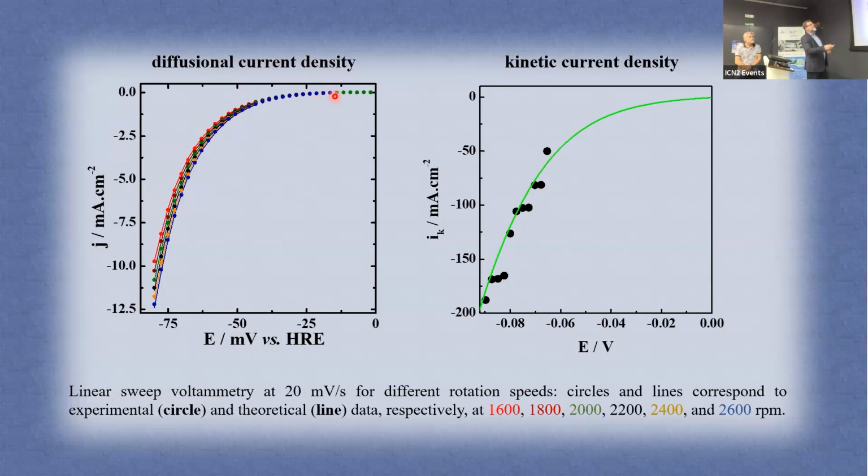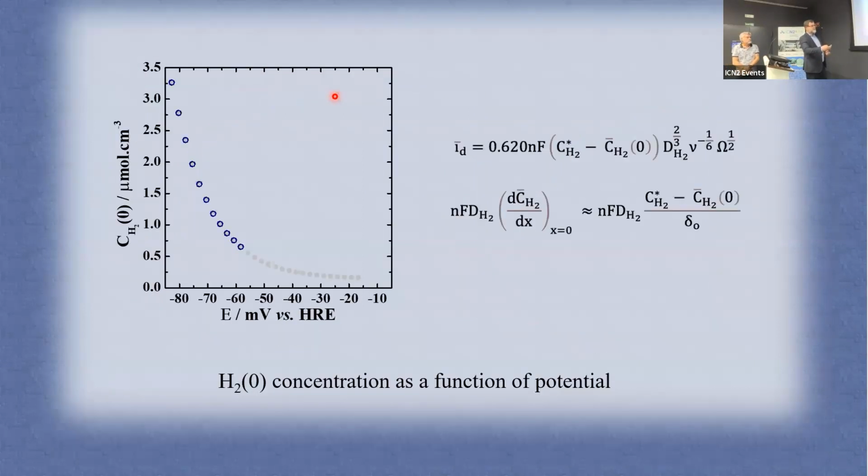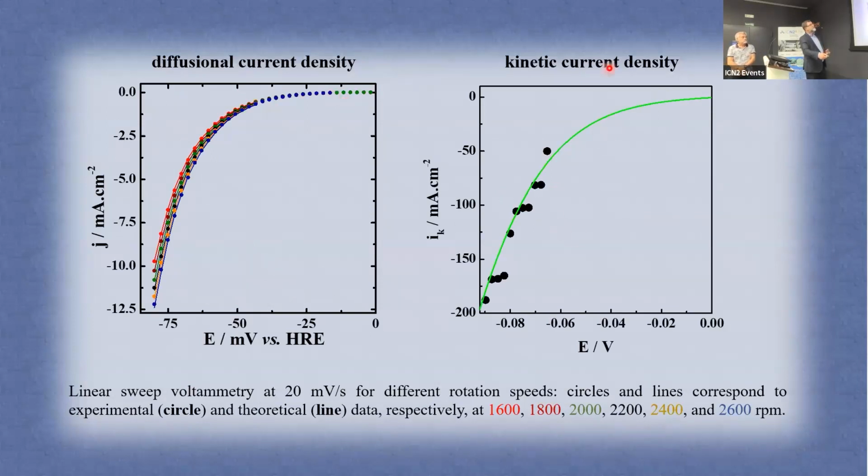This is the lime green. Oh, sorry. Here. This is the Butler-Volmer without mass transference. So we can observe at low overpotential there is the activation process. The limitation of the charge transference occurs at low overpotential. Okay.